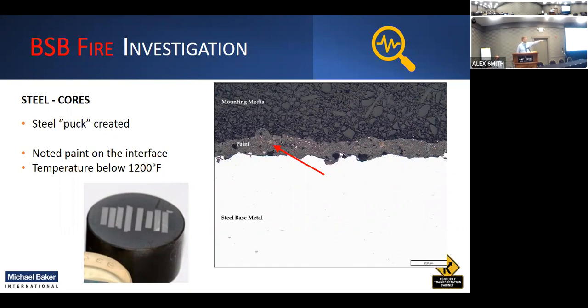So when they put it under the microscope, what you see in that right picture there, the dark portion is a mounting medium. The light portion of it there is the steel. It's very polished and bright. And you'll see a little bit of banding. They were able to say, hey, there is still some paint on this sample. And what that essentially tells them is that the fire didn't get above that 1200 degree threshold at which the fire would burn off the paint that was on the bridge.